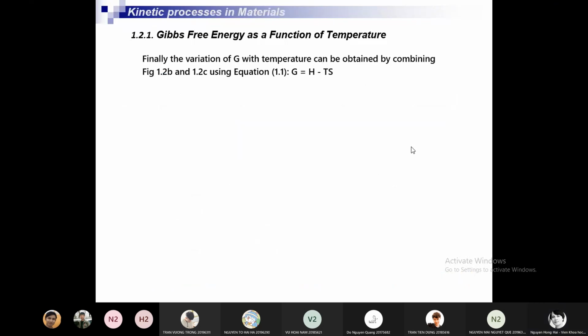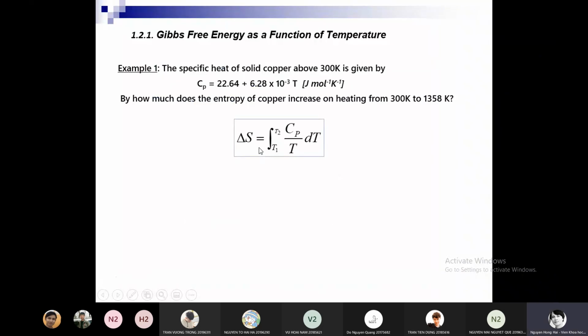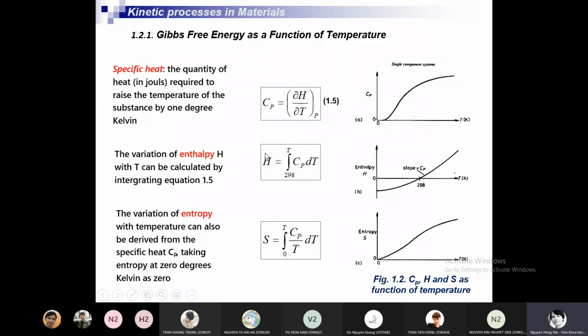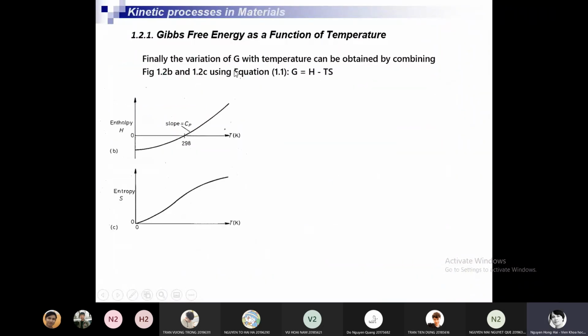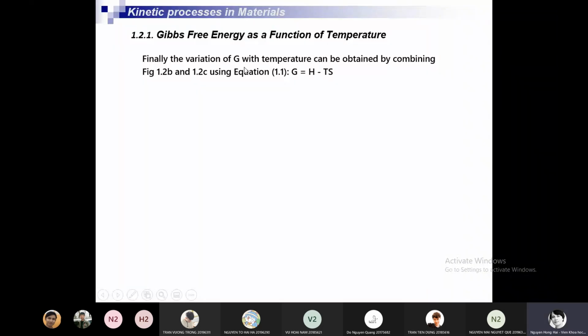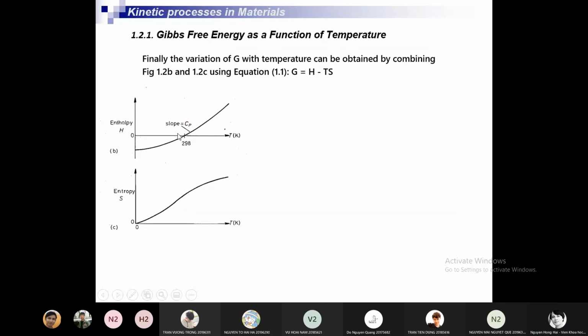Okay, and finally we can find the variation of the free energy with temperature. This is the most important. We have the variation of specific heat, of enthalpy, of entropy with temperature. The most important is the variation of the free energy with temperature. And this variation can be obtained by combining this figure, enthalpy and entropy, and using this equation: G is equal to H minus TS. You combine this enthalpy curve with the entropy curve, and with this equation, you can find the free energy.